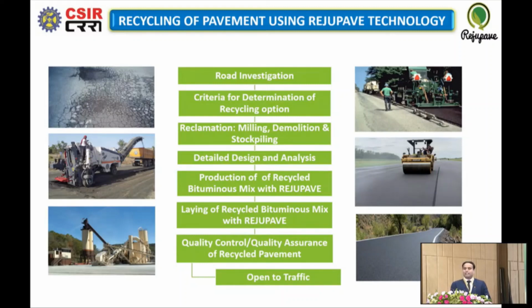So in place of it, when you put a new layer on top of it, you have to use natural aggregate along with the virgin bitumen and then prepare the fresh mix. Instead, what we can do is mill the material from the distressed bituminous surface, bring it to the hot mix plant or project site, and classify the RAP into coarse and fine RAP. Then we can develop a job mix using RejuPave rejuvenator, and 60 to 70% RAP material can be reutilized into fresh bituminous mix.